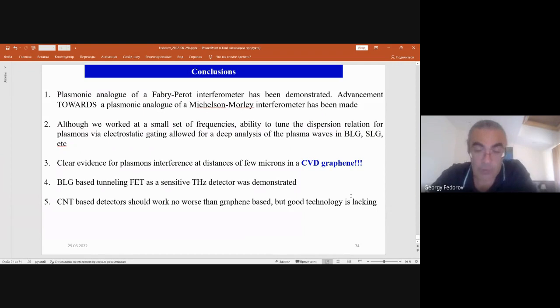And what is important is that we have clear evidence for plasmon interference at a distance of a few microns in CVD graphene. I didn't mention it, but the classical decay length for plasmons within the Drude theory that we used is about 100 nanometers. It's just the product of the plasmon velocity by the momentum scattering time tau, and it gives you about 100 nanometers. But we see something on a much larger length scale, so we believe it may demonstrate that plasmons close to the Dirac point will survive through longer distances than predicted by classical theory.